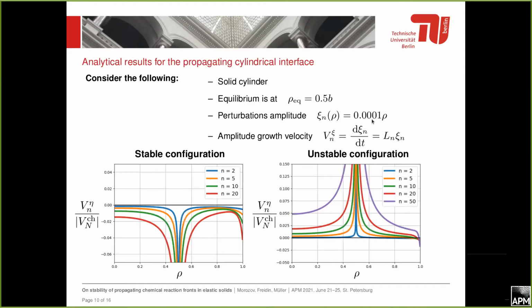And to see what is happening in a stable configuration, of course, we want to plot the ratio between these two velocities. By these two, I mean the velocity of the perturbation, so this index should be xi, not eta, to the global, let's say, kinetics of the interface. And this is basically the solution for the unperturbed interface propagating towards the equilibrium.